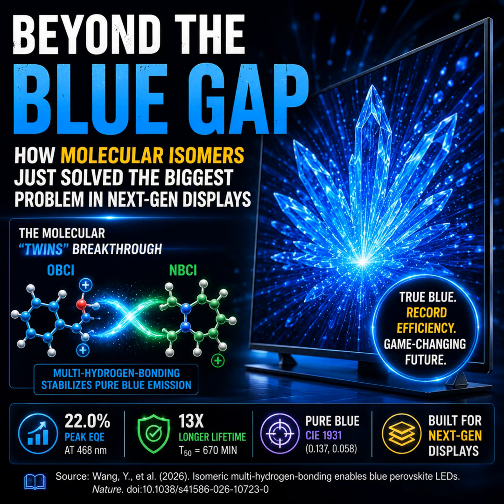Let's start with efficiency, which is measured in EQE, or external quantum efficiency. The control device, the standard one without the twin molecules linking arms, had a measly EQE of 5.7%. Just 5.7. Yeah. But the target device with the scaffolding skyrocketed to a record-breaking 22.0% for pure blue at 468 nanometers. And even when they pushed it to an even deeper blue at 463 nanometers, it hit 16.8%. We really have to emphasize that jumping from under 6% to 22% in material science is not just some incremental standard update. That is a generational leap.